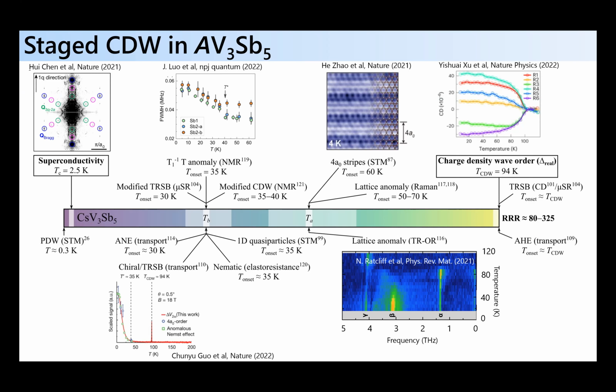And so this is just sort of capturing some of the stuff. So you start with charge density wave state where potentially you have some onset of time reversal symmetry breaking, depending on which probes are looking at it. And then there's an intermediate temperature scale around 60 Kelvin or so, where short lifetime lattice modes turn on, as seen via optical measurements. At the same time, charge stripes are pinned at the surface, as seen via STM measurements. Raman sees lattice anomalies at this same type of intermediate temperature scale.